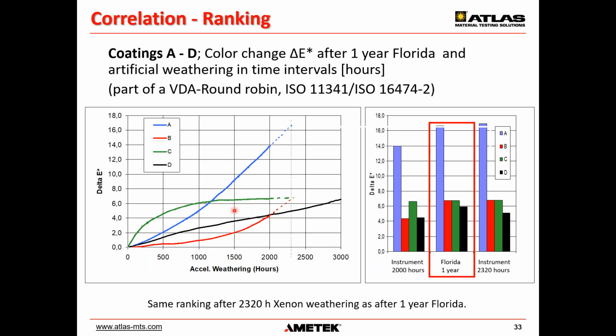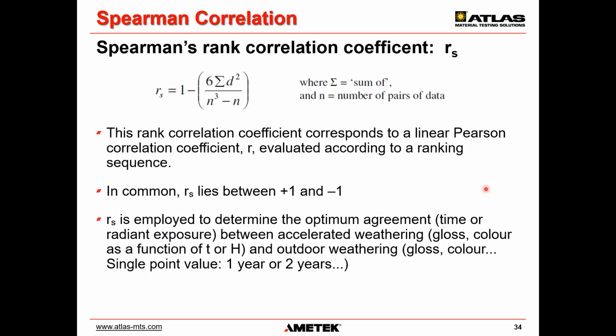of 3,000 hours. So in the beginning, the green material C, it was not really a green material, it's just shown here as green, material C shows the fastest aging, but then the color change is decreasing. Material A is almost linearly increasing, D is linearly increasing. B is the best in the beginning, but then suddenly the fading, the color change, is actually increasing. So the ranking is changing continuously in the exposure. And the best time for comparison to Florida in this example would be for the instrument exposure after 2,320 hours, where we have almost the same ranking as in the Florida exposure.